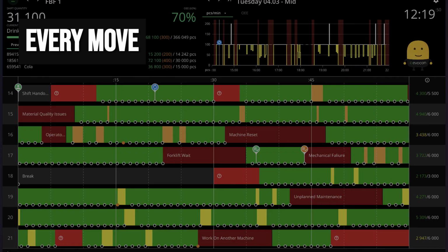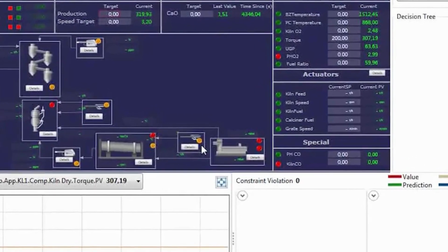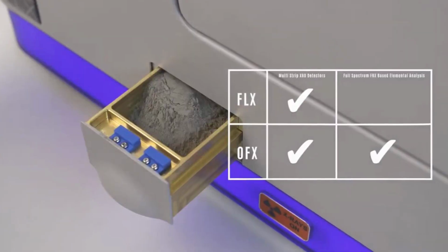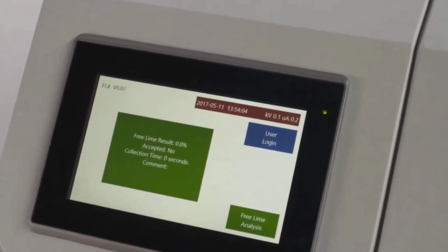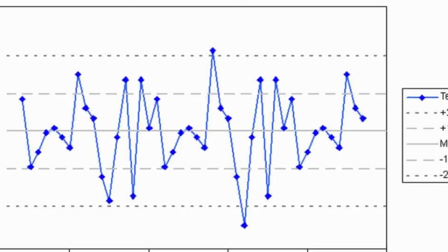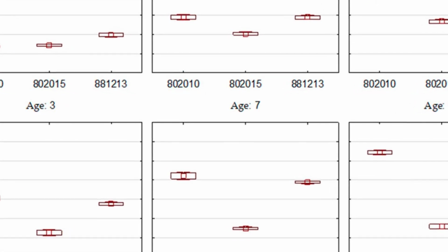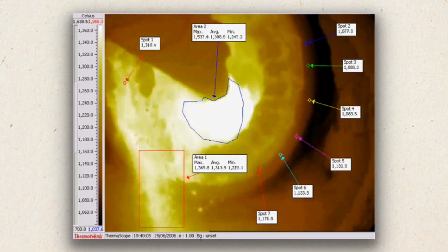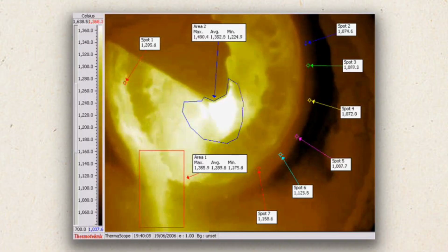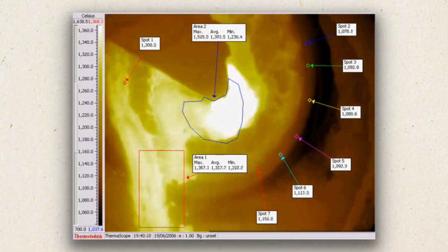The system logs every move, each valve position, every analyzer reading, and the calculated effect on free lime and kiln stability. Over time, the impact is clear. Free lime variation is cut by half, and the risk of overburning or underburning in the kiln drops sharply.